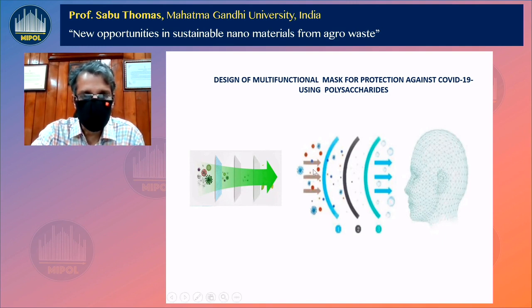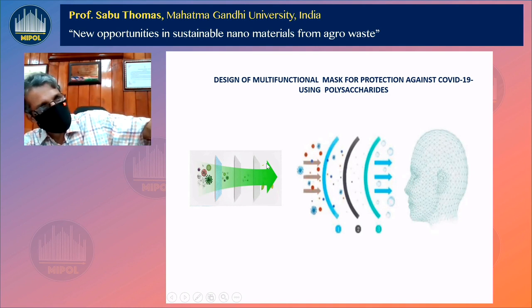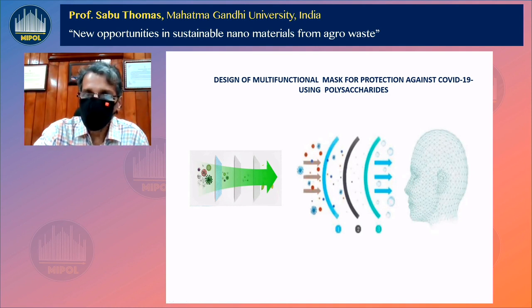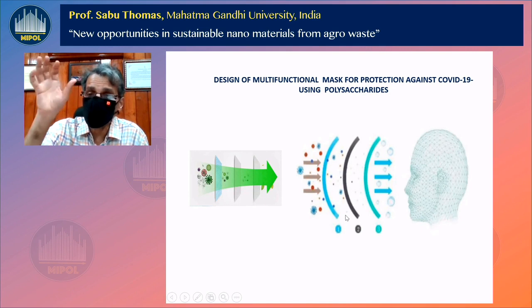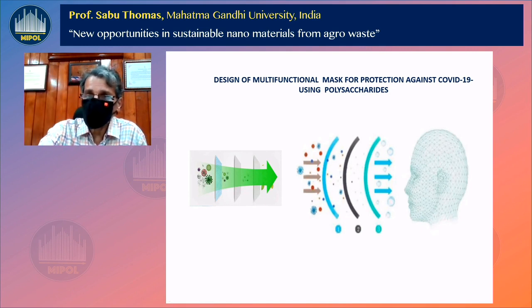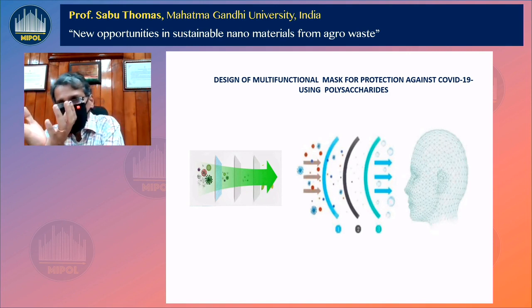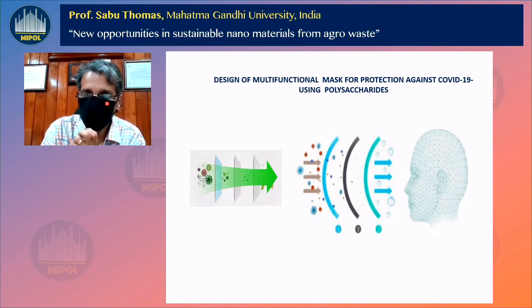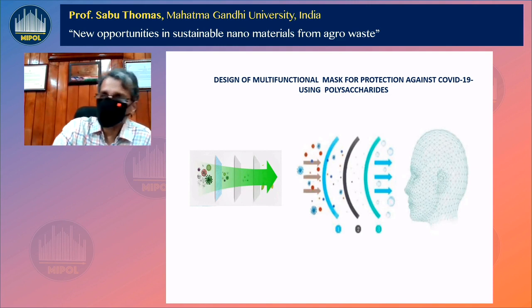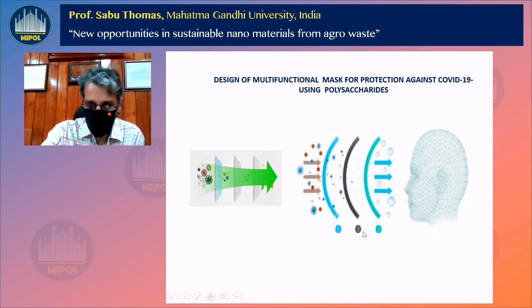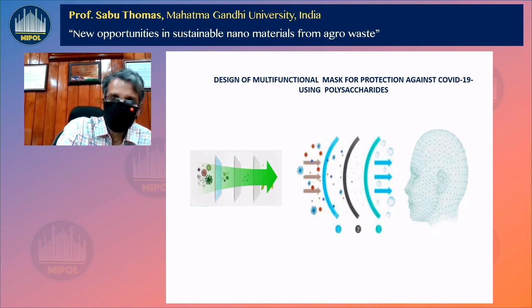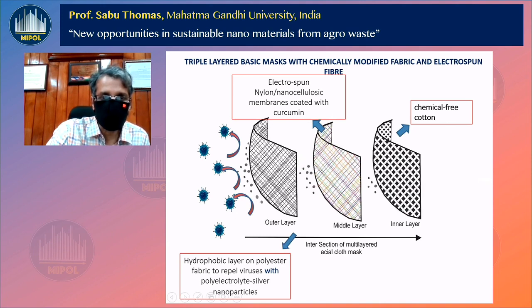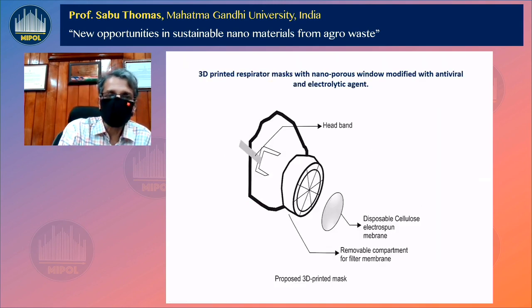So this outer layer can drive away the coronavirus because it is anti-adhesive and highly hydrophobic. If at all some coronavirus gets in, if you're careless in wearing the mask, this middle layer can kill the coronavirus because it has positively charged nanocellulose. This positively charged nanocellulose can interact with the negative charge on the virus. The virus could be deactivated. The innermost layer is a very comfortable coating, in contact with your mouth. This is our mask configuration: the outer layer, the middle layer, and the inner layer. We also propose to make it by 3D printing.